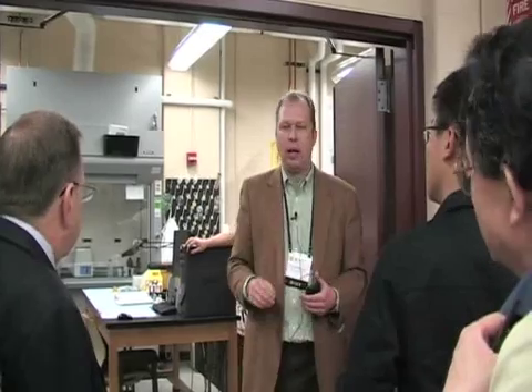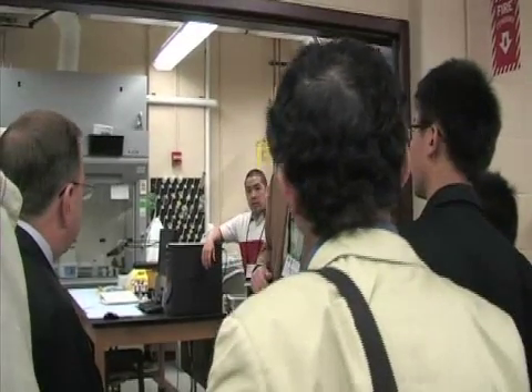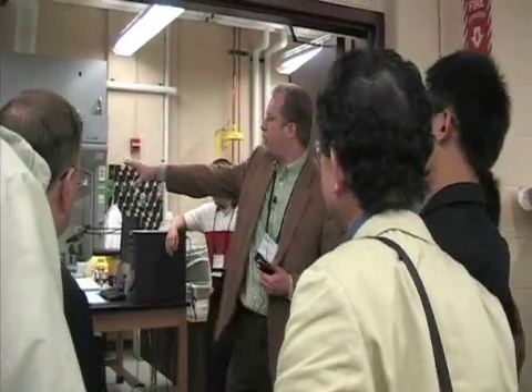One of the work that we do in the micro end milling realm here is look at diamond coating, very thin, conformal and continuous diamond coatings. The main reason for going thin is to not blunt the edge radius or whatever features we put on the tools. We grow our own diamond coatings in here. The reason they're nanocrystalline is we're trying to make 100, 200 nanometer thick coatings. We need to be able to grow small crystals with that. We have a small chemical vapor deposition reactor.